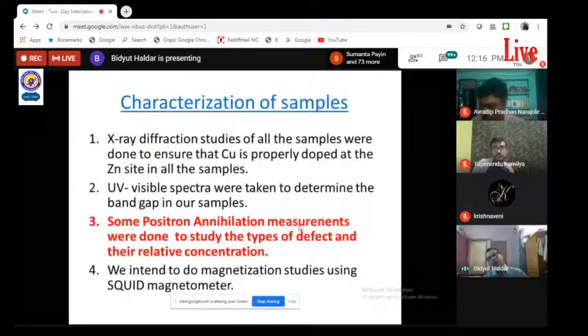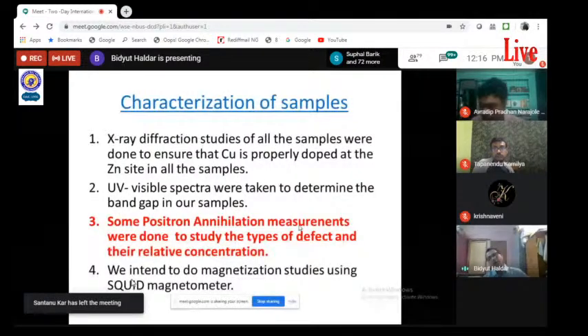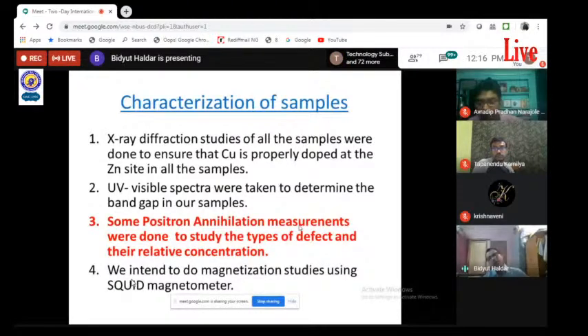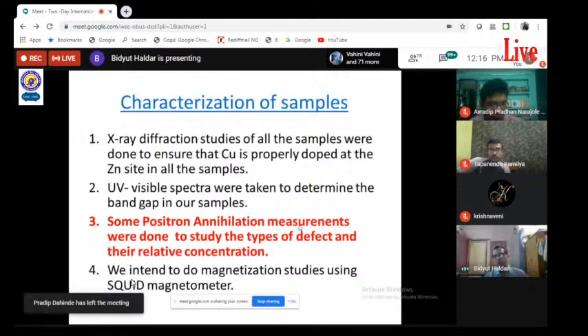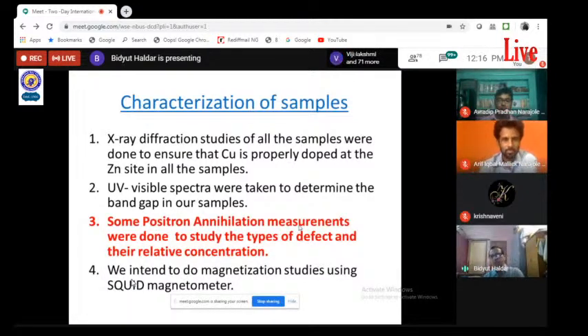We did X-ray diffraction to ensure whether the copper is properly doped at the zinc site in all the samples. UV visible spectra were taken to determine the band gap in our samples. Some positron annihilation measurements were done to study the type of defects and their relative concentration. This particular study, the third one, is of importance in this topic, and it is still on because of the lockdown, we are unable to do more measurements. And finally, we intend to do some magnetization studies using SQUID.